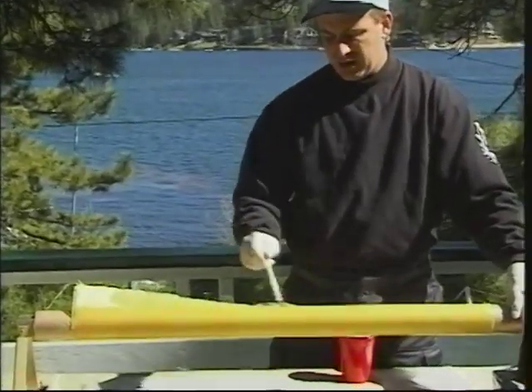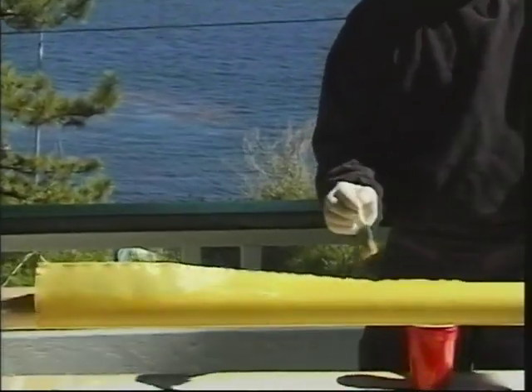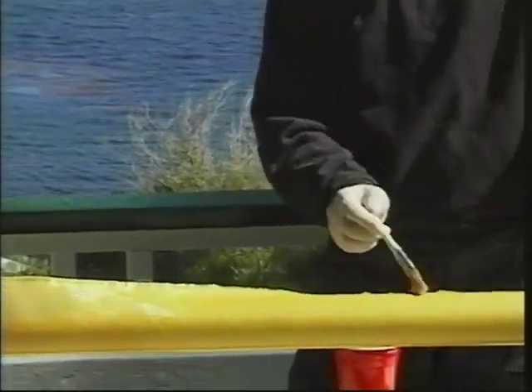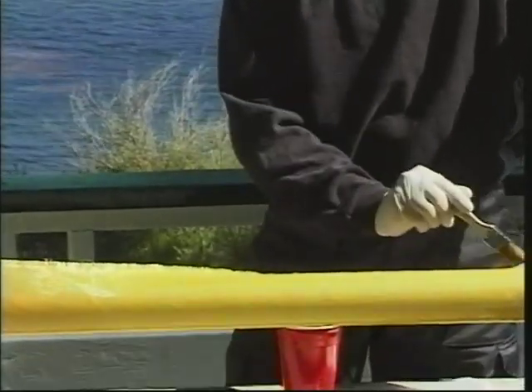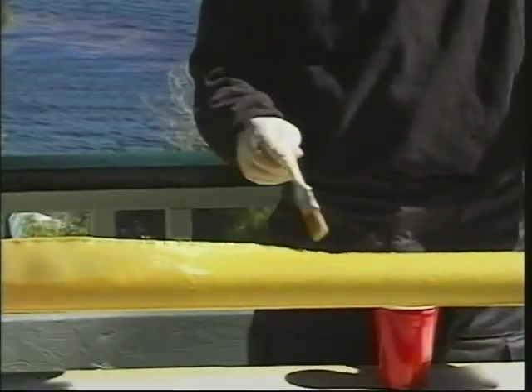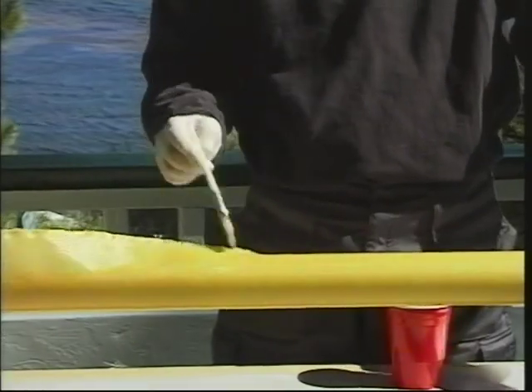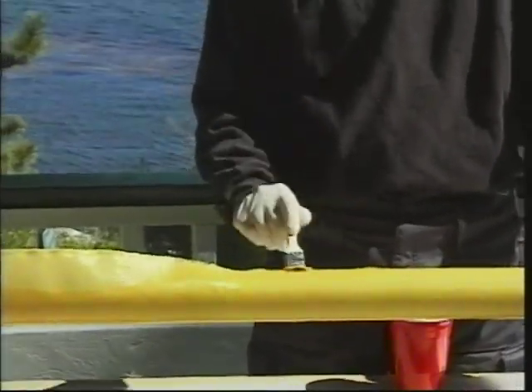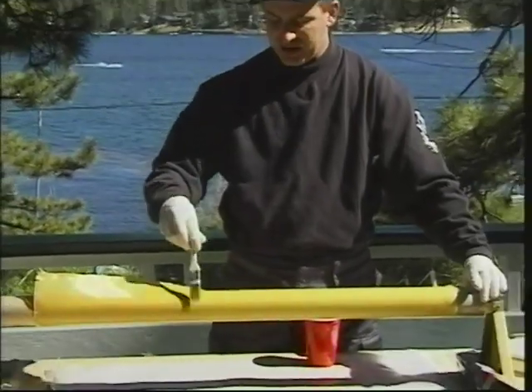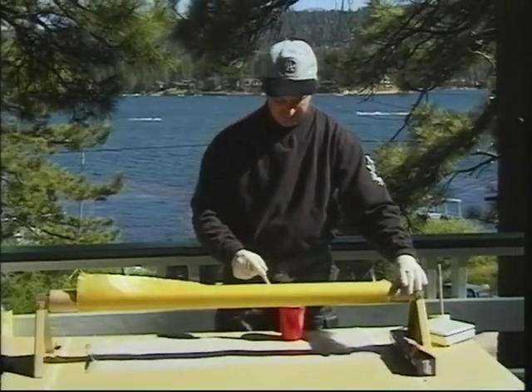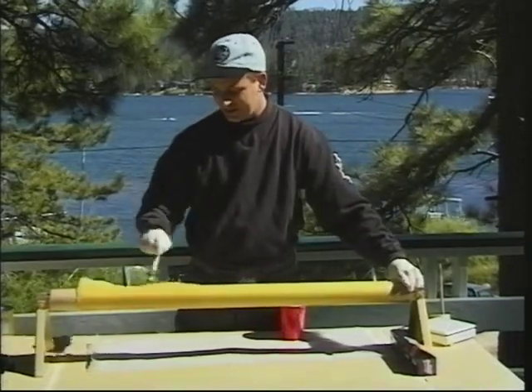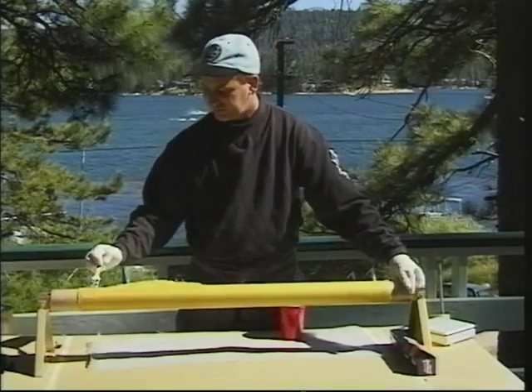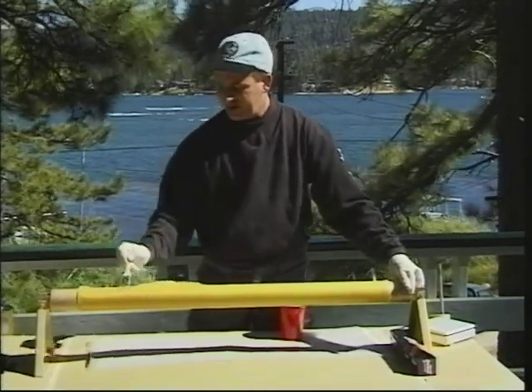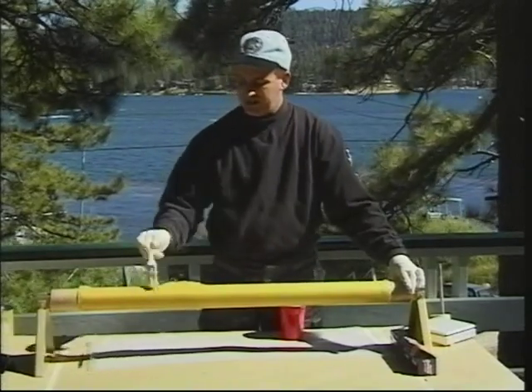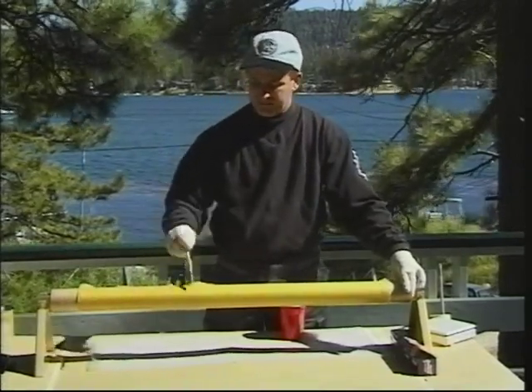So just working around the tube. Again, I'm coming to the end of my wrap, so just using the rolling technique to make sure that last end is down there. I don't have to be hypercritical about it because the tape winding is going to happen after this, but I like to get all the fibers near the ends saturated as well, so everything is soaking with resin. Notice it's not dripping with resin, it's just soaked with resin and saturated. Try to get that 50-50 resin to reinforcement ratio.